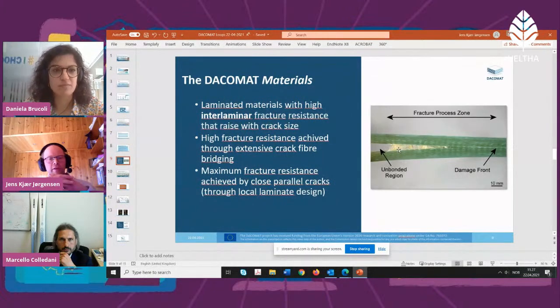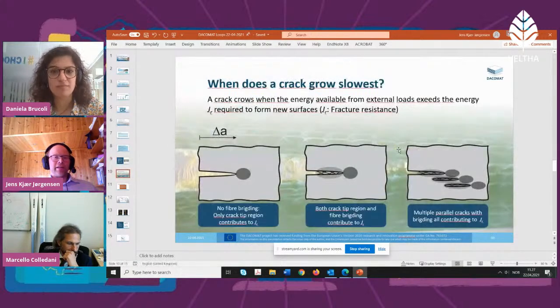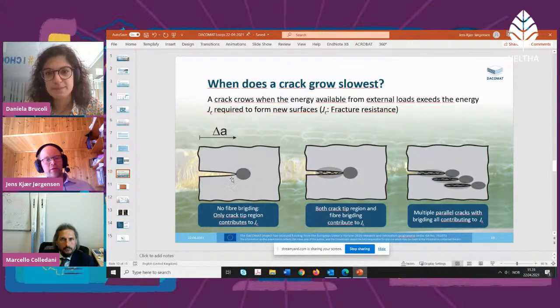And in addition, we're looking at the concept of multiple cracks, so close parallel cracks, which, if you have close parallel cracks, increase the overall fracture resistance. A little more about the technicalities. What actually makes a crack grow slowly? For a crack to grow, if you look here at the left figure, you need to deform the crack material, and that requires energy. And that energy is taken from strain relaxation in the whole structure.